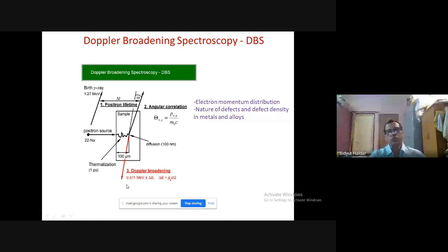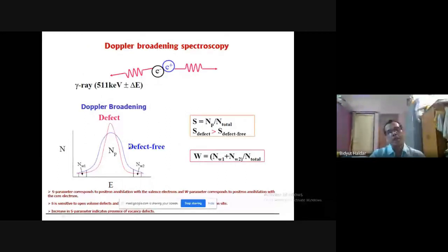As a result, the energy of the gamma ray, which is supposed to be 0.511 MeV, gets broadened, and this broadening depends mainly on the momentum of the electron with which the positron is annihilating. So it depends on the electron momentum distribution and the nature and density of defects in metals and alloys. This is a typical Doppler broadening spectrum, and you can see the difference between a defect and a defect-free spectrum. The wing parts are very important because they come from the momentum of the core electrons. Positrons like to go to places which have defects. From this spectrum, by calculating two parameters known as the S parameter and W parameter, we can find the relative concentration of defects and also the kind of defects in the sample.